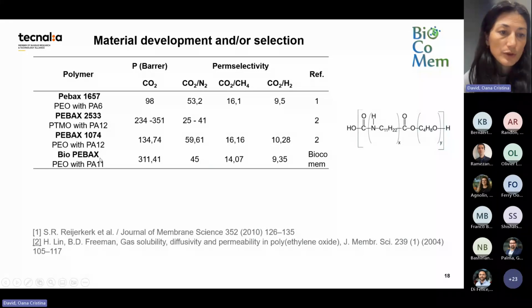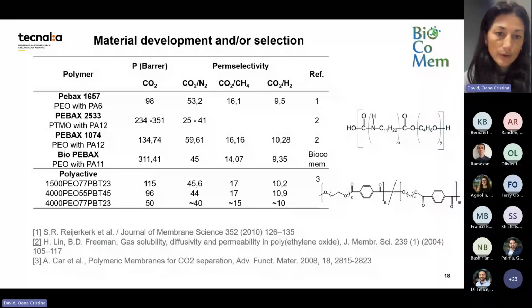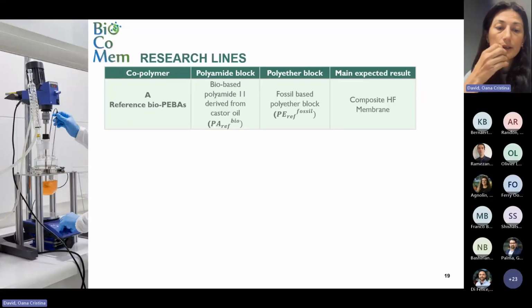And then when we started the project, we decided to work more with these polymers because we observed in a project before that we have these PEBAs with polyamide 11, which is bio-based, coming from castor oil. We have observed that it has a much higher carbon dioxide permeability. So we decided, here I'm showing also PolyActive as we showed before, that it is interesting to work with this polymer.